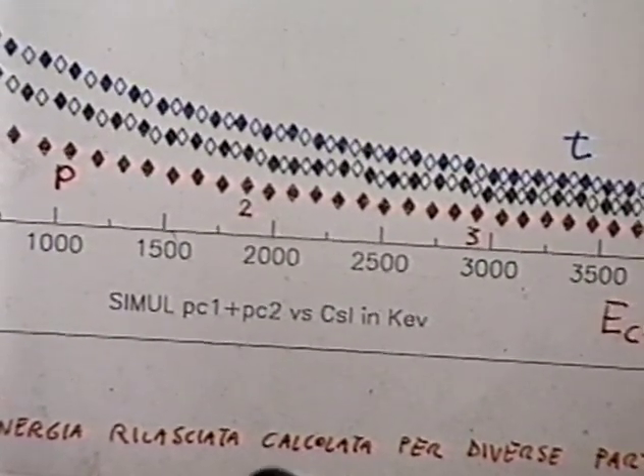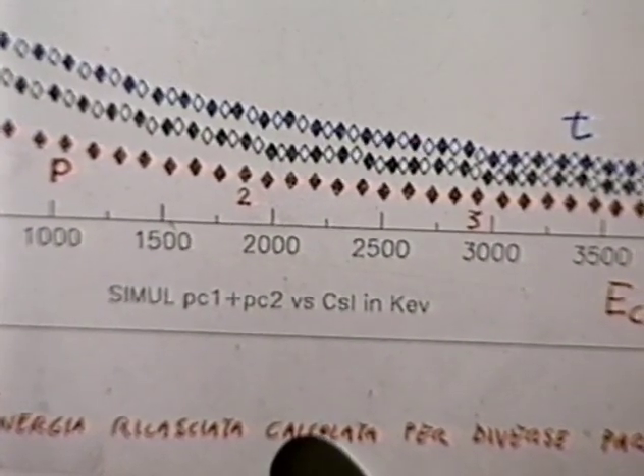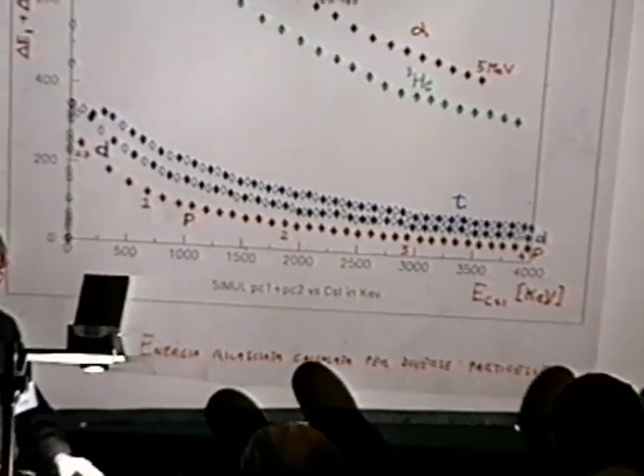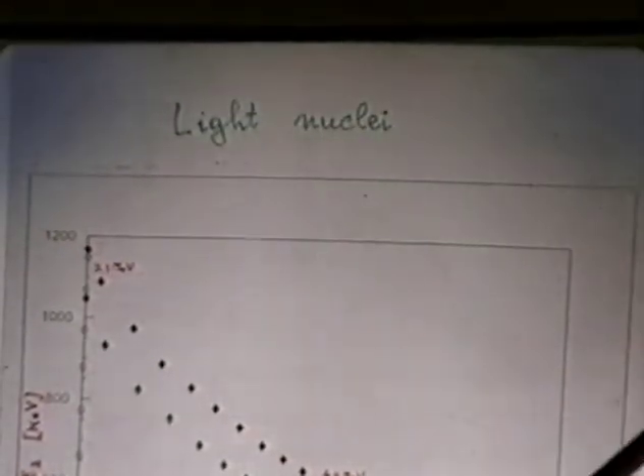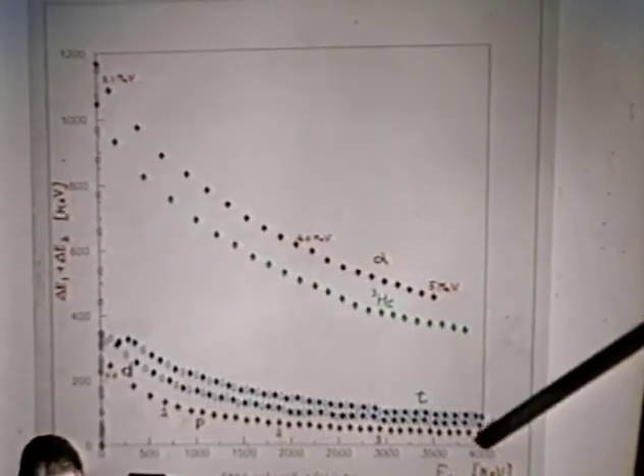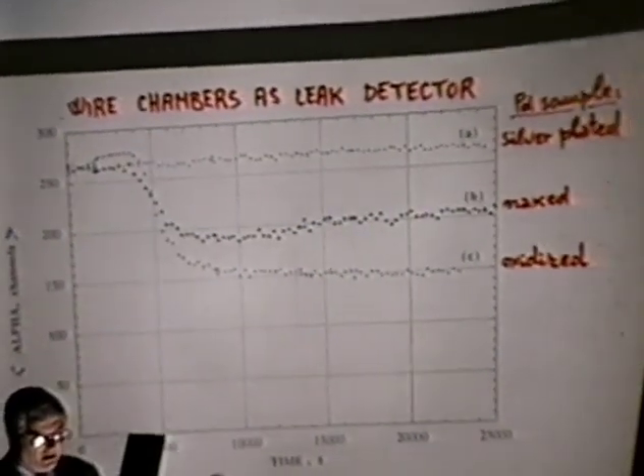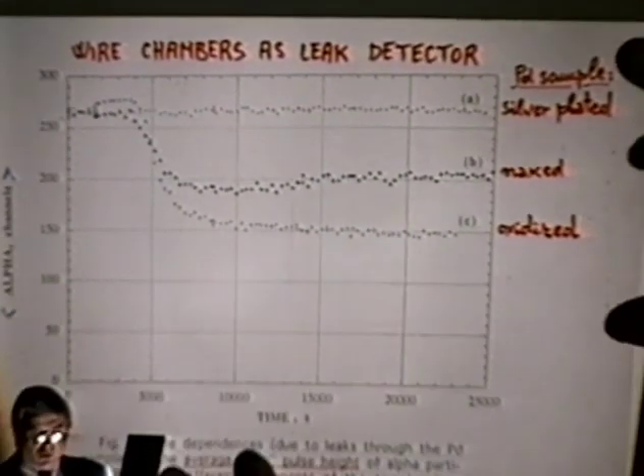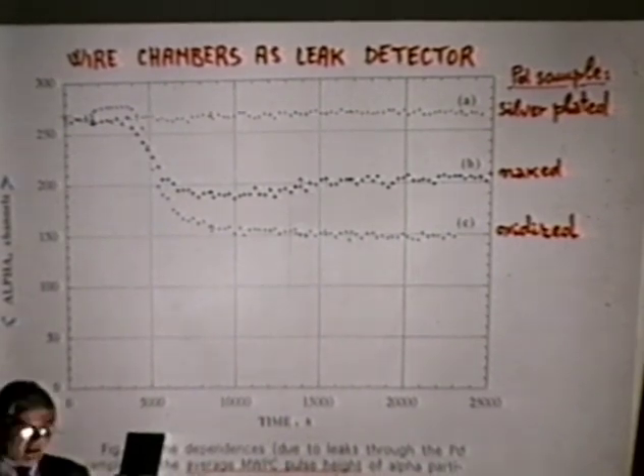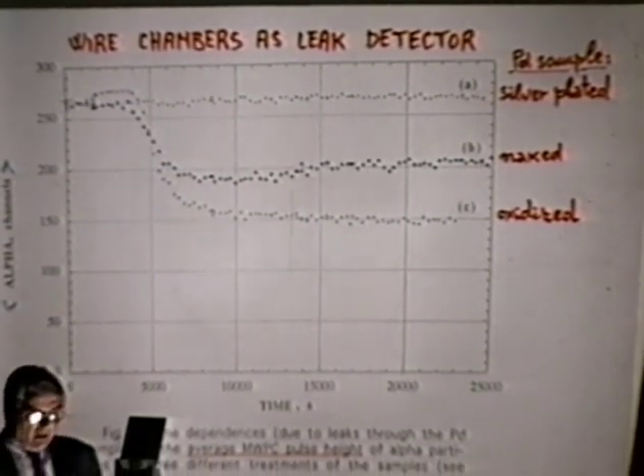In this way, we could expect to detect light nuclei, and this is the average expectation for light nuclei. For instance, alpha particles at 90 degrees, not the source ones, from 3 MeV to 5 MeV, helium-3, tritium, deuterium, of course protons. And protons now are much lower because the scale has been compressed. Unfortunately, when the palladium is loaded, the deuterium could go out toward the wire chamber, and then it would disturb the wire chamber pulse height.